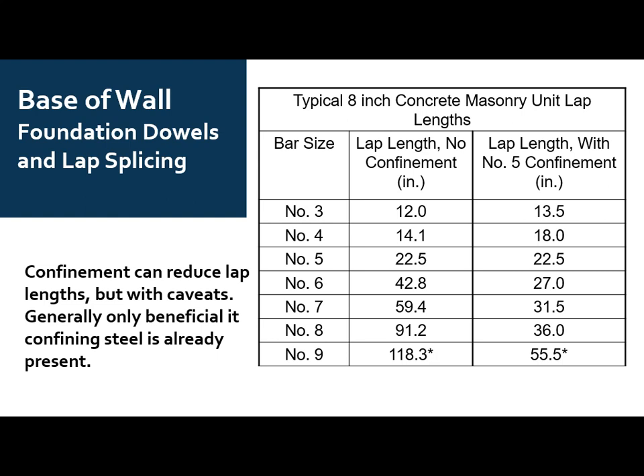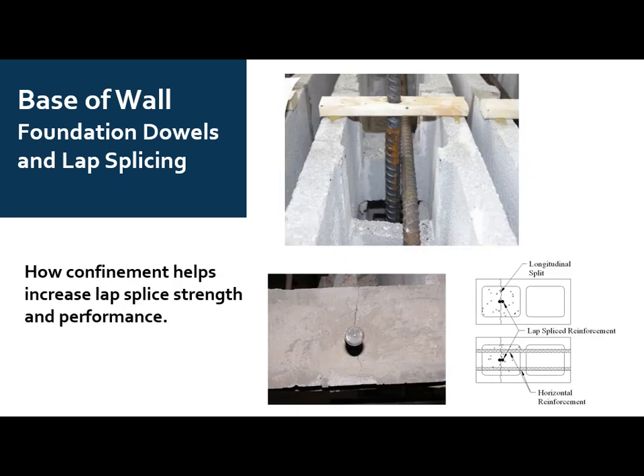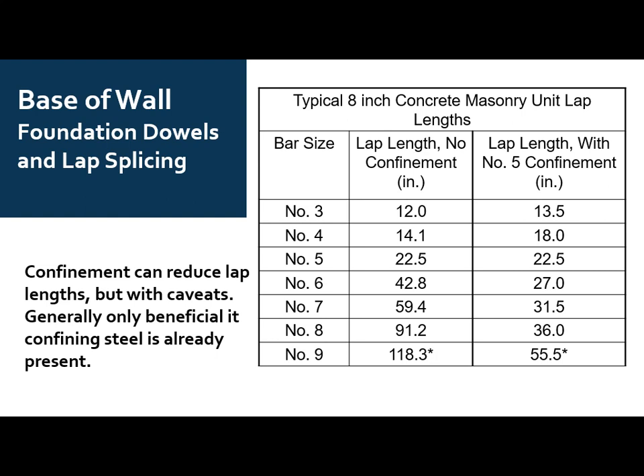To give you a punchline, if we ran the numbers using that equation for different bar sizes, and this is all for 8-inch block centered in the cell, we have a lap length for each bar size based upon no confinement, and of course a lap length with the confining steel. The first thing you might notice is for the small bars, the lap length goes up, which doesn't make a whole lot of sense, but it's how the math works out for this particular scenario. The reason is there's a minimum lap length associated with this confining steel to ensure we don't have that pull-out failure mechanism. We don't want that smooth bore left in the masonry grout after you load up the reinforcing steel.